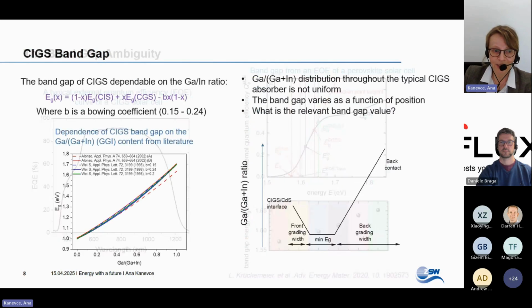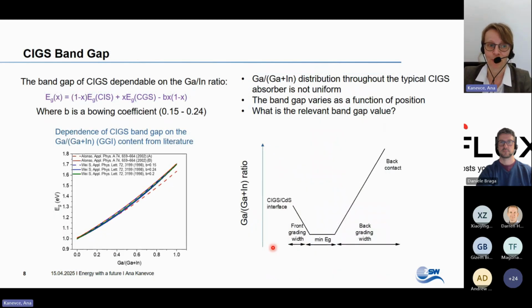Now in CIGS, this is even a little bit more complicated. I mentioned before the bandgap can be varied with gallium versus indium ratio. Theory and ellipsometry say yes, but this is a parabolic function. It has a bowing coefficient, and this bowing coefficient varies depending on other things. For example, it varies as well with the copper amount in CIGS.